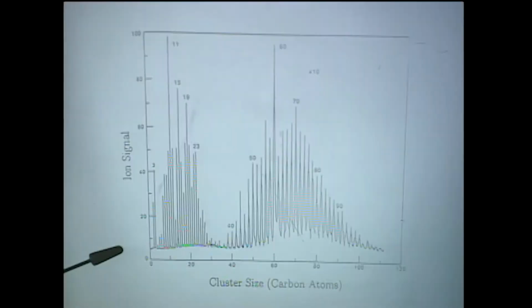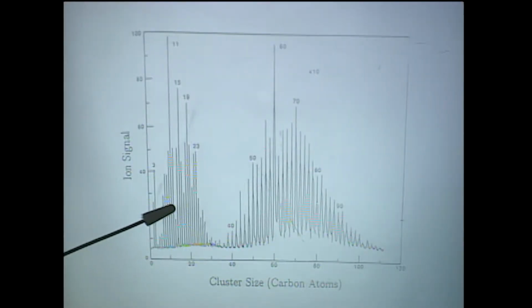One of the things that we were able to do was to figure out how much material left the surface when we applied a certain amount of energy with a laser to the surface. So we had some idea of the energy balance. And we knew that the carbon had to come off in large chunks. But at the time that we did the work, it was only known that carbon clusters existed in very small numbers, like C2, C3, C5s. Even C10s were not very common. Around that time, I visited Exxon and talked about our work, and they assured me that there were no higher fullerenes, higher clusters of carbon.